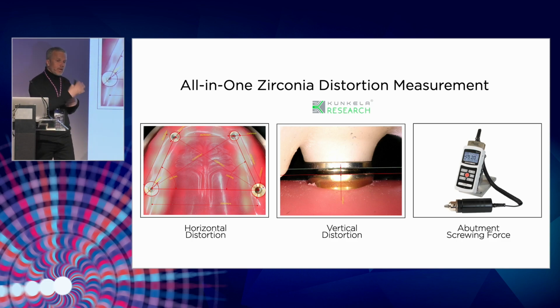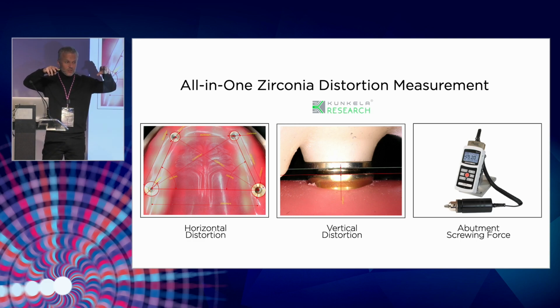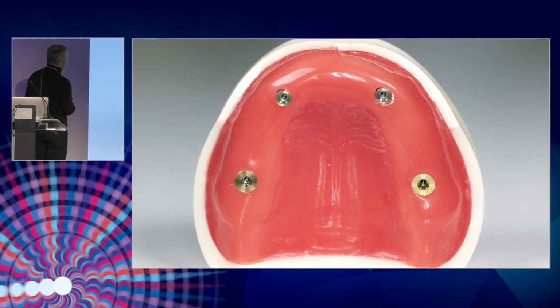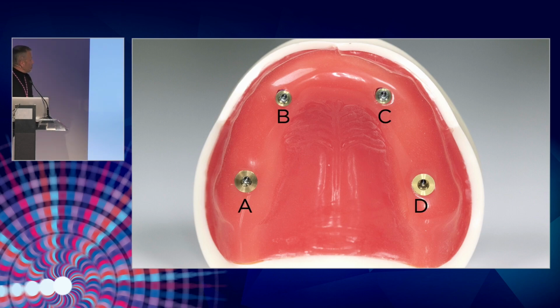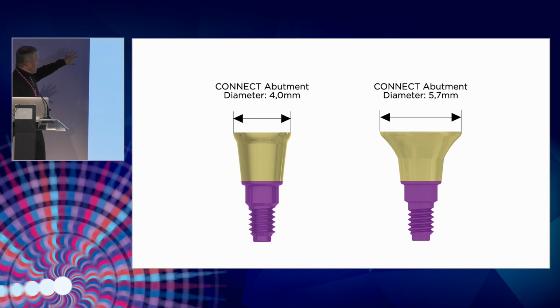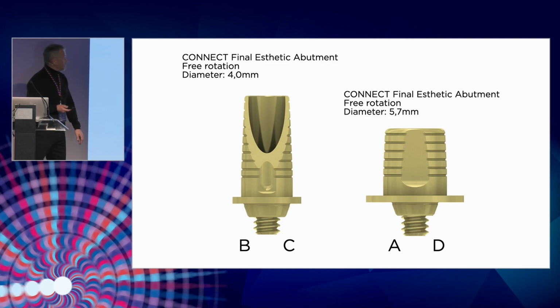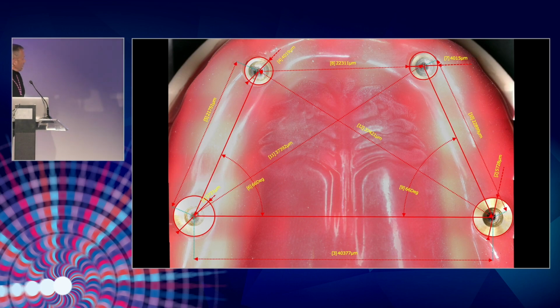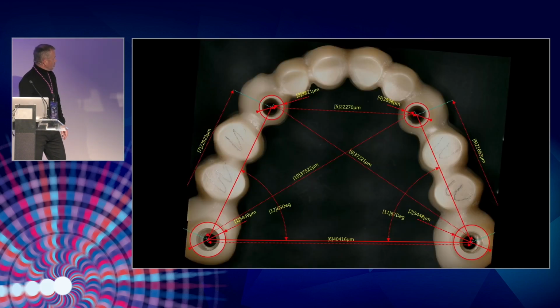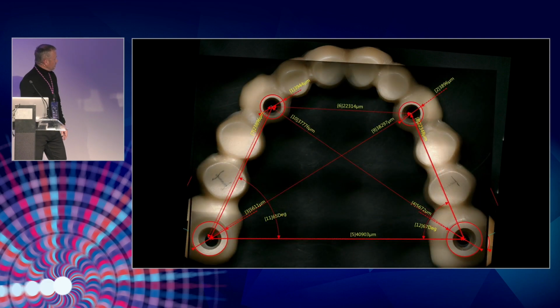This is what we evaluated: horizontal distortion, vertical distortion, and also the force of screwing abutments, because at the beginning all the frameworks fit to the abutments, but there was a really big difference in how much power we had to use to fit all 4 parts of the implants. For horizontal distortion measurement, we used an electronic microscope. We measured these A, B, C, D distances at the beginning, and we screwed them onto one-time abutments. In the anterior zone it was 4 millimeters and posterior 5.7 millimeters, and we bonded these Ti-bases with free rotation into the restoration, because they are designed to work like this.